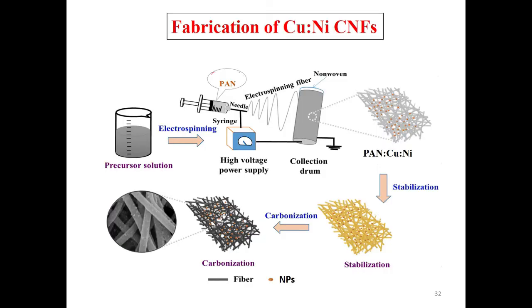Now the next is the fabrication of copper nickel carbon nanofiber. Here is the precursor solution we have used. Electrospinning is done with the help of this particular material, and there is a formation of PAN copper nickel nanofiber. Carbonization is done, and because of the carbonization it is converted into the carbon fiber.